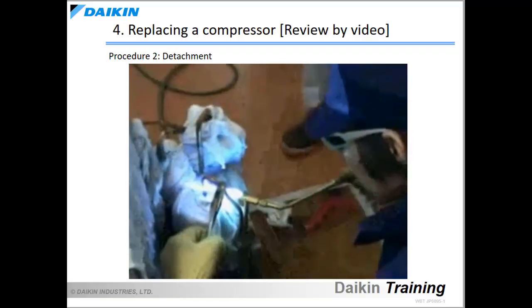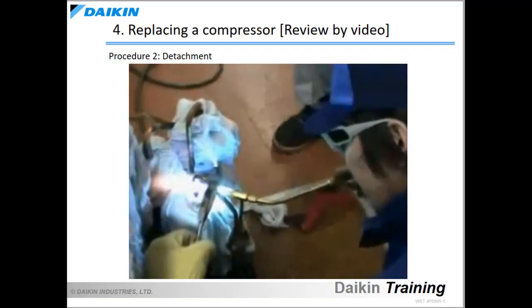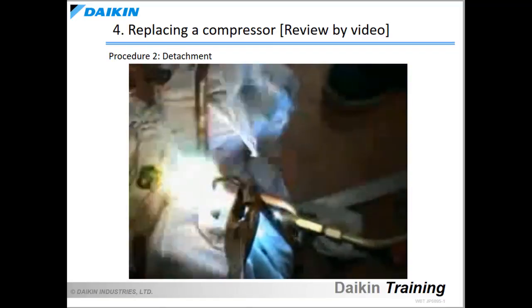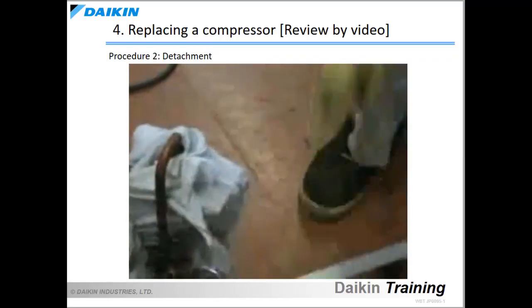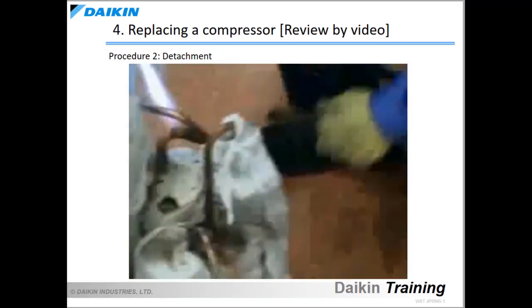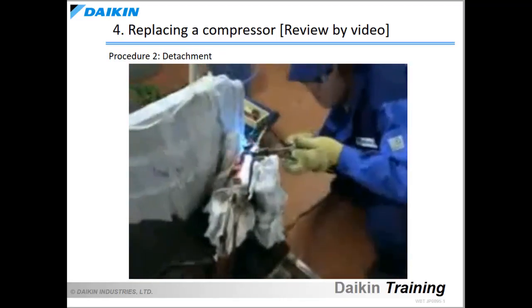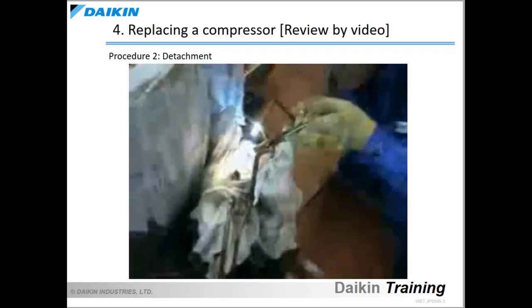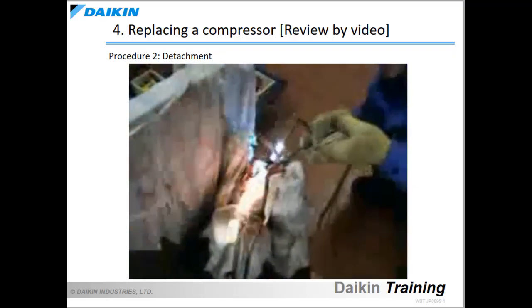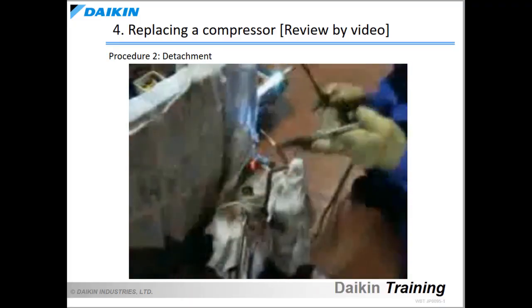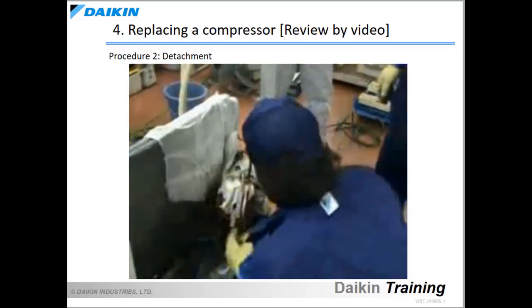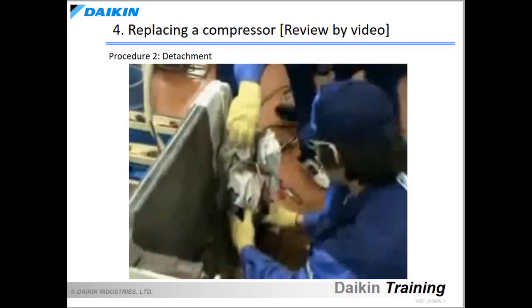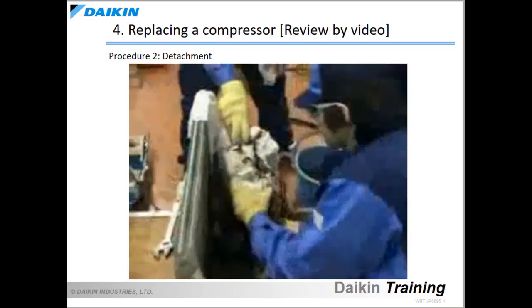While performing nitrogen replacement, heat the brazed area of the discharge pipe on the compressor with a welding torch and remove it. If oil is still inside the piping while the compressor is being detached, it is very dangerous, as the oil will blend with the refrigerant gas and the brazing heat will turn it into asphyxiating toxic gas. Moreover, the oil can be ignited by the brazing flame and create a pillar of fire. Therefore, detach the compressor as far away as possible from your face. Heat the brazed area of the suction pipe and remove it.